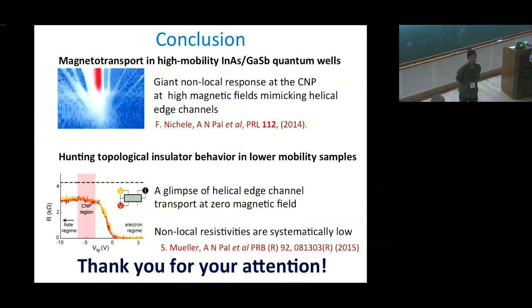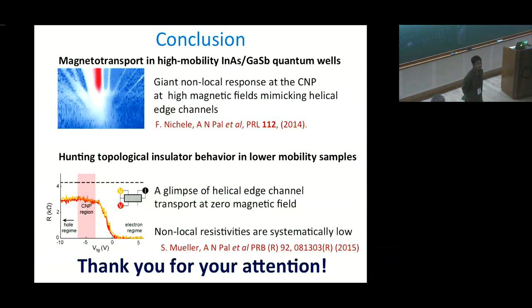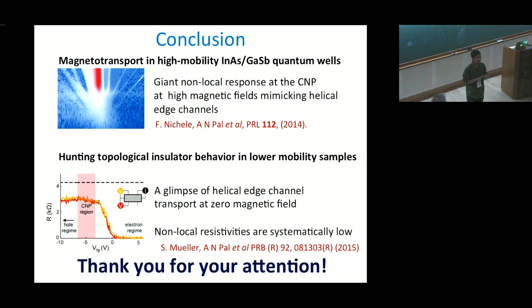Question about the S-type Hall behavior: naively, it goes as one over density for both holes and electrons, and in the coexisting region you get an S-type curve. The width or sharpness of the S reflects something like puddle-like structure, as known from graphene. In this case the feature is not very sharp — it's quite skewed out. This suggests the charge neutrality point could differ across the sample because it is a large millimeter-sized sample with disorder throughout.